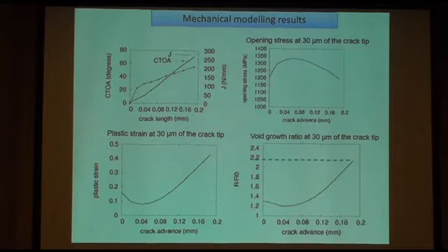This ratio is taken at the crack tip, so we constantly move the element as a function of the crack advance, and as we propagate the crack, we start to reach, about 200 microns from the onset of cracking, the level at which ductile fracture will take place.